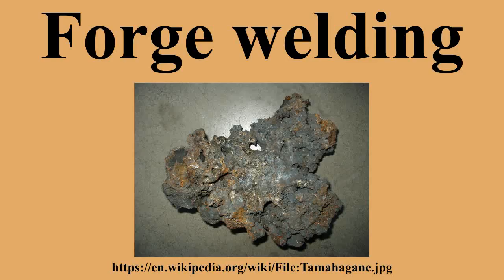When mechanical hammers were developed, a forge welding could be accomplished by heating the metal, and then placing it between the mechanized hammer and the anvil, originally powered by water wheels. Modern mechanical hammers can also be operated by compressed air, electricity, steam, gas engines, and many other ways. Another method is forge welding with a die, whereas the pieces of metal are heated and then forced into a die which both provides the pressure for the weld and keeps the joint at the finished shape.